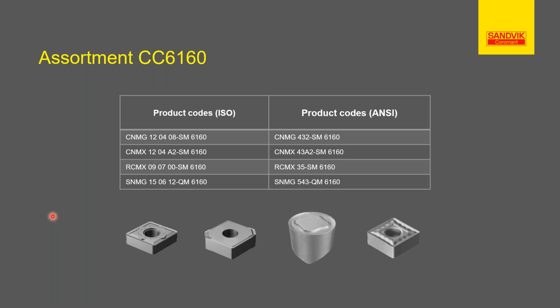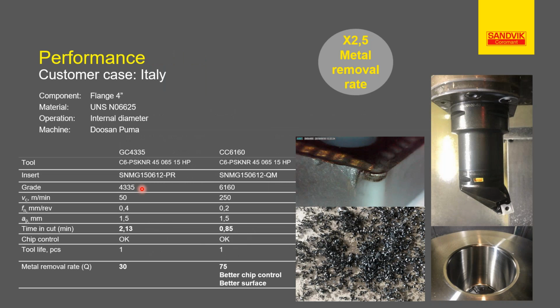We have different shapes, so CNMG, CNMX, as you can see here, SNMG, all with this chip breaker that allows you to remove the chip. And this is a real example on a flange. In this case, we see the insert in 4335 and in ceramic. You can see here we move from a speed of 50 meters to a speed of 250 meters with a metal removal rate of 2.5 times, as you can see here. And the chip is perfect. It is very small. It is better than with the carbide insert. So better chip control, better surface, and better metal removal rate.